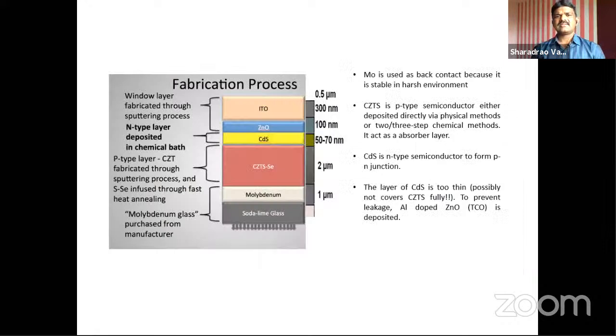We can see here the fabrication process to develop, to fabricate the solar cell. First of all, we require a substrate. The substrate may be glass on which you have to deposit one special kind of layer, like here we used molybdenum, because we have to anneal all the setups at more than 400 degrees Celsius, and our soda lime glass will not sustain in that harsh environment. That's why we use moly as a back contact, because it should be stable in a harsh environment,